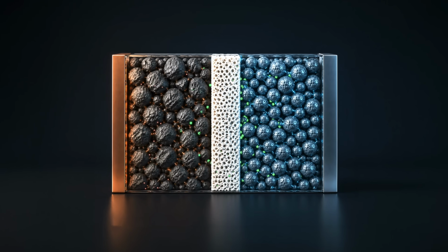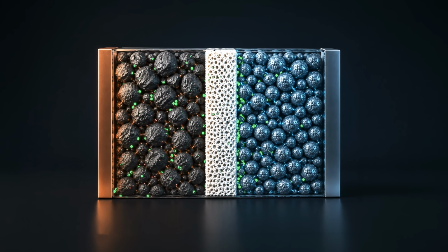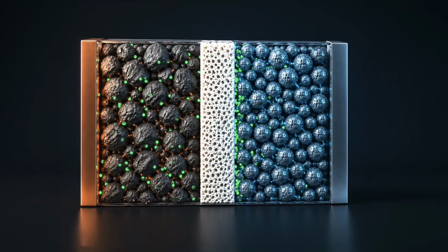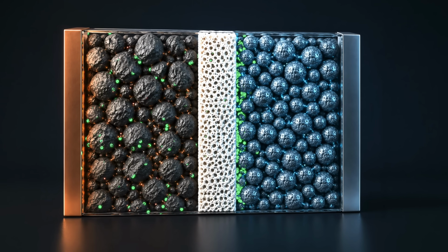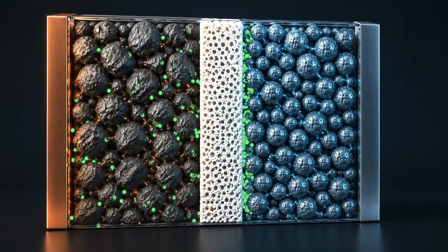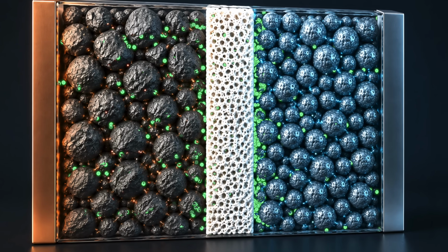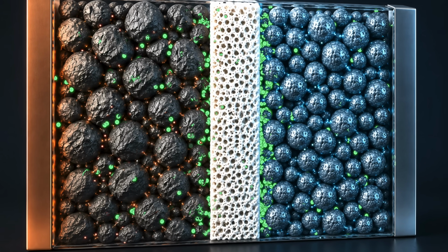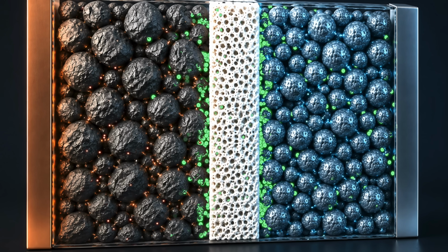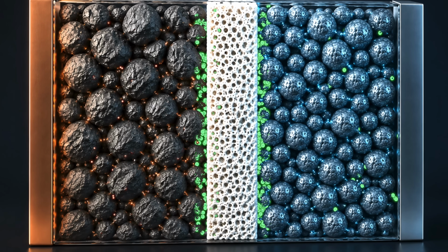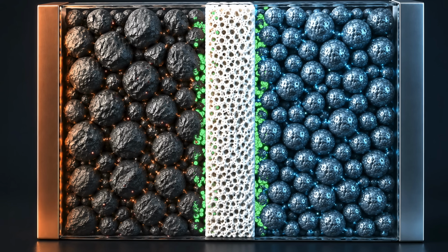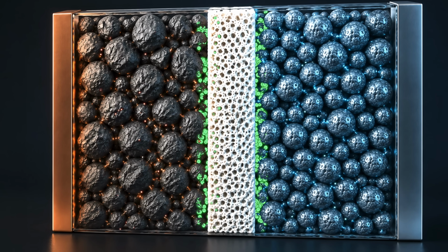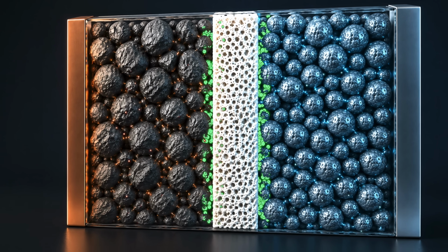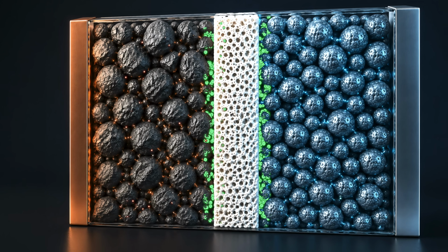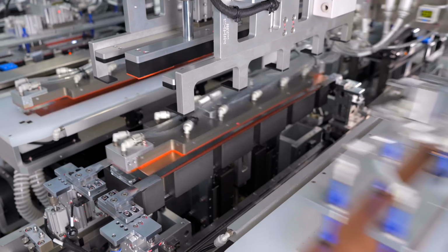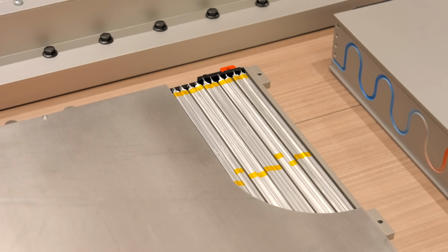But there's a nuance worth getting right here. Every brand new battery, solid-state or not, goes through a process called formation. It's the first few controlled charge cycles right after the cell is built, where the chemistry settles into its final working geometry. The active materials expand in place for the first time, and the internal interfaces lock in. Think of it like breaking in a new pair of shoes. But once that formation finishes, typically a handful of cycles, that pressure comes off and the cell operates at exactly 1 atmosphere for the rest of its life. A gentle squeeze during break-in versus 800 atmospheres forever. It results in lighter, safer, and cheaper packs, and that unlocks the real market potential of next-generation batteries.